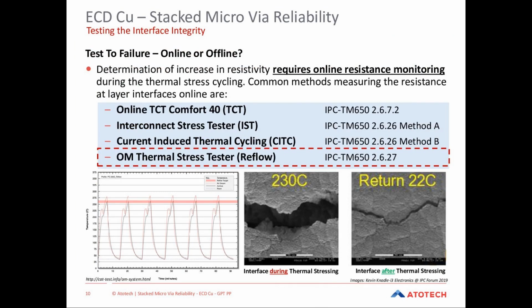What is important in testing the interface integrity is that you determine the interface connection while you apply the thermal mechanical stress to your build-up. That means you have to measure the resistance of your build-up while you apply this thermal stress, because during the thermal stress, the expansion of the printed circuit board is very high, and only in this condition will you have the highest resistance, which you need to determine, so that from its prediction, you can then assume when your build-up will be failing.